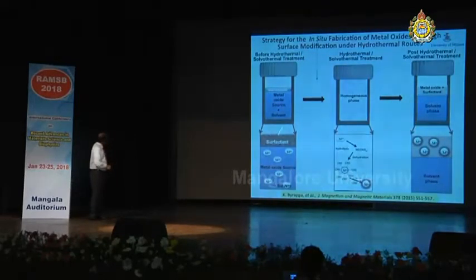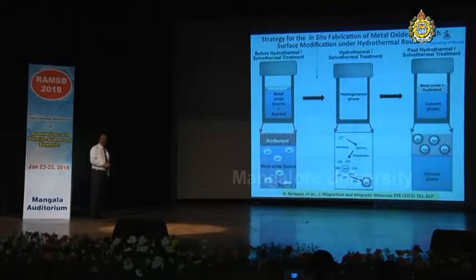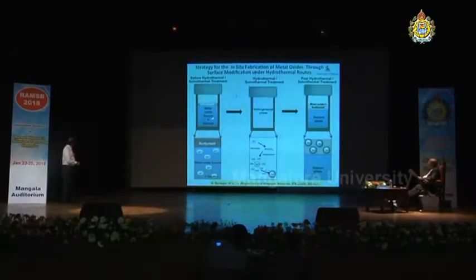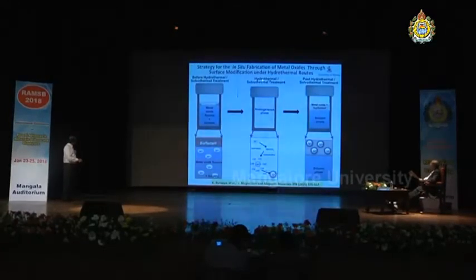Well, under normal conditions before the hydrothermal or solvothermal treatment, the fatty organic acids like oleic acid or gluconic acid and so on will remain at the top, as you can see here, the top layer, and your solvent may be organic or inorganic. Normally this represents the aqueous solvent, and the metal oxide source existing separately, as you can see the species. And during the hydrothermal or solvothermal treatment, you have the homogenization of the raw materials, and the hydrolysis or dehydration reactions occur, and you have the formation of such metal oxide or hydroxide species which have the organic coating around.